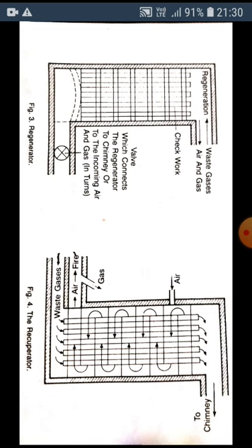At the same time, air and gas are heated in a heated regenerator. The temperature which is thus attained is higher than the temperature of the flame from air and gas without heating them. The direction of the ingoing air and gas is reversed after every 25 to 30 minutes, during which one set of regenerators gets considerably cooled because of loss of heat to air and gas, and the other set of regenerators gets heated up because of absorption of heat from the waste gases.